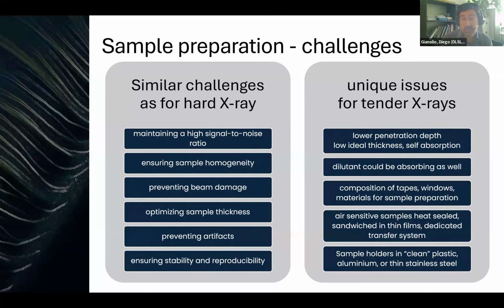Then another problem is that when you prepare pellets for hard X-rays, the common procedure is to dilute the sample with boron nitride or cellulose. But for tender X-rays, the dilutant material also starts to be absorbing. And so you can use only a very small amount, and you need to be careful about what material is used. And not only about the dilutant, there is the need to be careful about any material that is used for the sample preparation, since they could contain some of the elements that have an edge in the tender X-ray range. So it is very important to study the composition of tapes, windows, or any material that is used for the sample preparation.